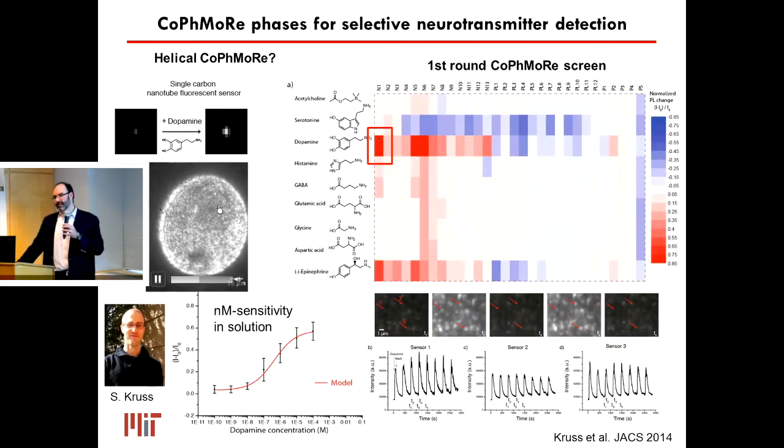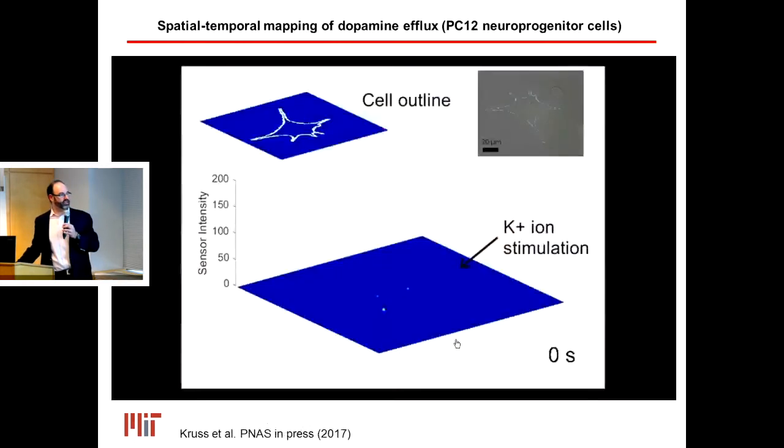So the chemists never got around to making a fluorophore reporter for dopamine. It's such an important molecule, right? But it just never happened. So you can put carbon nanotubes on a surface. That's what you're seeing here. And Sebastian is just dosing 1 nanomolar solution of dopamine. You see this very bright turn-on response. It's very unique, and it's very reversible. You can see this here. It's very fast-acting and reversible. Remember, just 1 carbon nanotube on a surface is an addressable nanosensor.